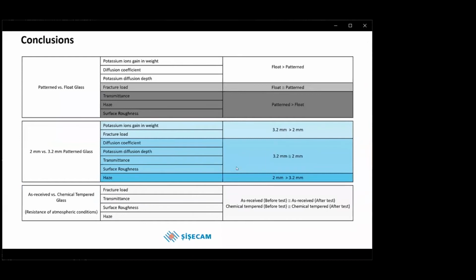And when all the results are evaluated, it has been proven that low iron pattern thin glasses instead of float glass can be used as a cover glass, obtaining a higher efficiency in the photovoltaic systems without any loss of mechanical properties.